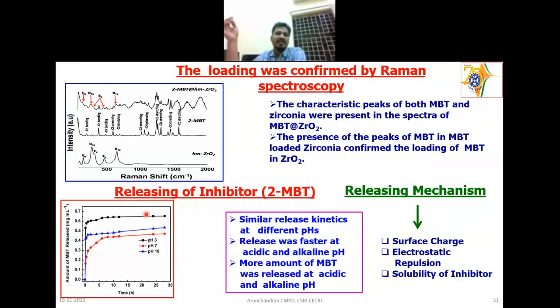One such strategy is that you use different pH solutions. Why pH? When corrosion happens, the important thing is that pH changes. Anodic areas will be acidic pH, cathodic areas will be basic pH. So when the pH changes, this container senses that and then releases. We found that at pH 3 and pH 10, there was more amount and faster release compared to neutral pH. The release mechanism may be based upon the surface charge difference between the container and the inhibitor molecule in the acidic and alkaline environment, the electrostatic repulsion between these two, and the solubility of the inhibitor.